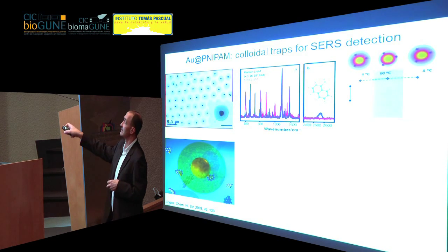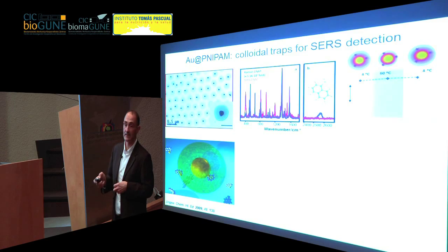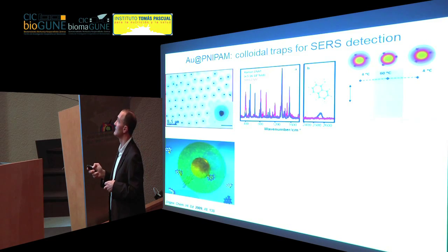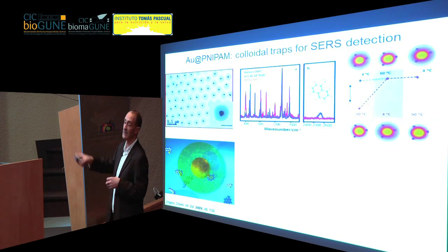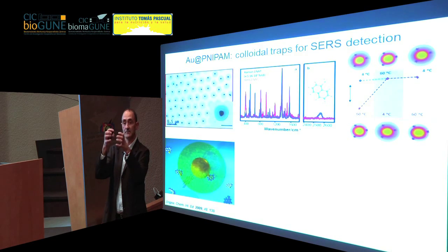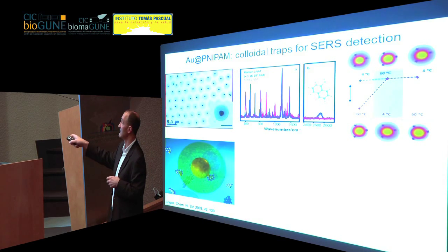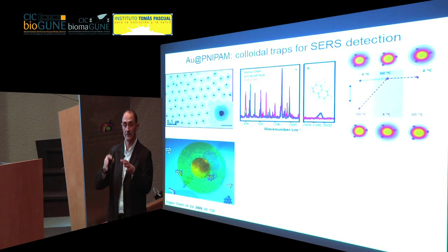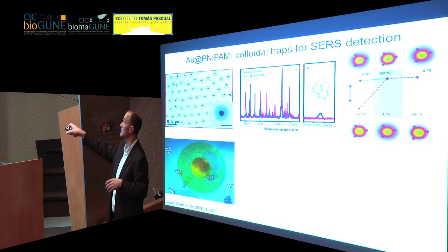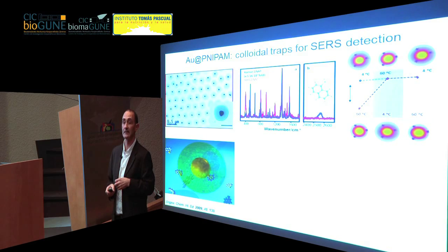In this case, regardless of temperature, you see the same intensity, except if you start at high temperature, when the microgel is collapsed, the pores are very small, so it's very difficult for the molecules to diffuse. And then if you lower temperature and let the pores expand, then you see again the increase in the signal, exactly the same as if you started at low temperature.